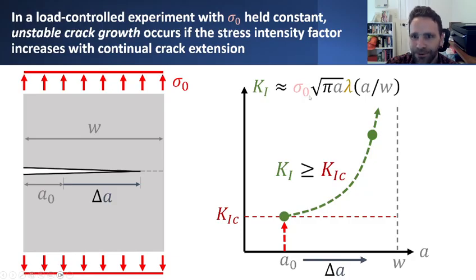And even though we're holding sigma naught fixed, what's changing is the crack size, A. As A continues to get bigger and bigger, as the crack extends even just a little bit, the stress intensity factor will change. And in the case of this particular plate geometry, we'll notice that it actually increases. This lambda will increase as a function of A divided by W, and this square root of pi times A term will also increase as A increases.